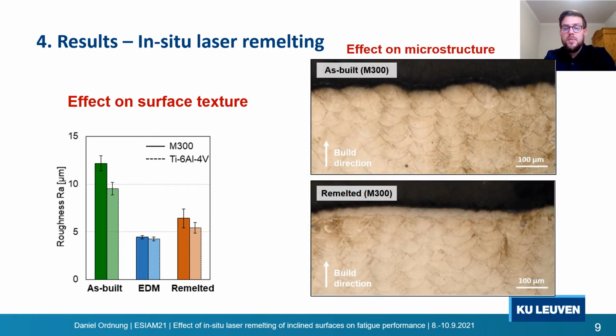Another effect is when we look at the microstructure. Here in the top picture we see the microstructure of the as-built sample. It shows the martensitic cellular microstructure for maraging steel with its melt pools and the melt pool boundaries. In the bottom picture we see the remelted sample. Here in the bulk material, the microstructure is similar, but if we look closer at the top surface, we see a concise remelted layer of about 50 micrometer thickness. This layer shows no traces of pores or lack of fusion.